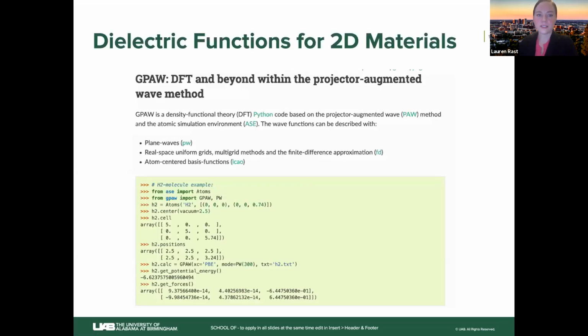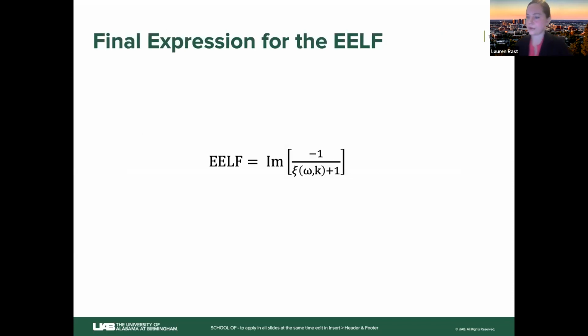Okay. So there are a lot of these DFT codes out there. I liked this one because it can do time-dependent calculations, and you can connect it to something called the Bethe-Salpeter equation, which is good for calculating spectral properties of materials. So the final expression for the electron energy loss function, which is going to create our model spectra, is given there. We just take the composite dielectric function and then calculate that.